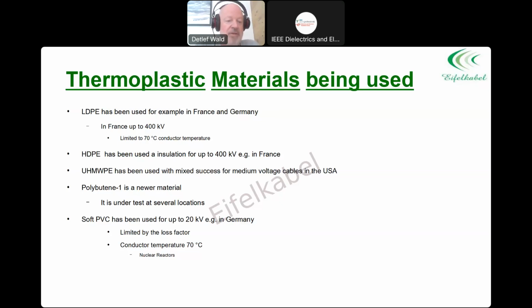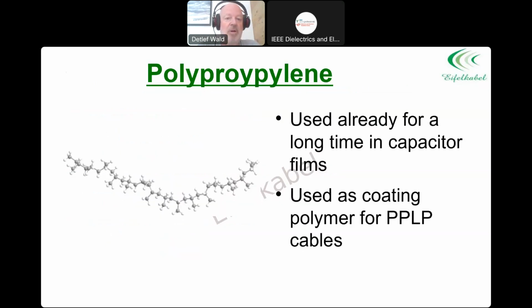Then also for medium voltage, soft PVC has been used for up to 20 kV, for example, in Germany. The cables are still in their network. The limitation for higher voltages there is the loss factor, and also the conductor temperature is 70 degrees. In nuclear reactors, it's used as a cross-linked FR version, according to my knowledge, but I'm not going too far into this. Just to give you some background of other thermoplastic materials.